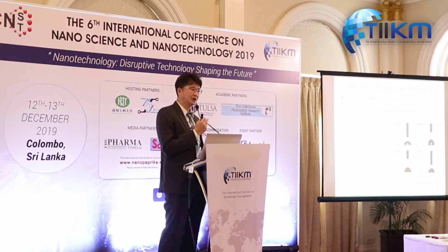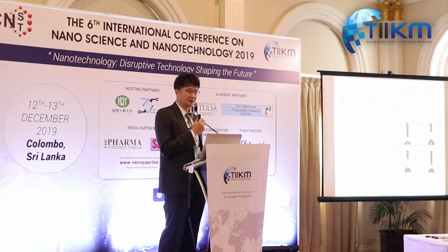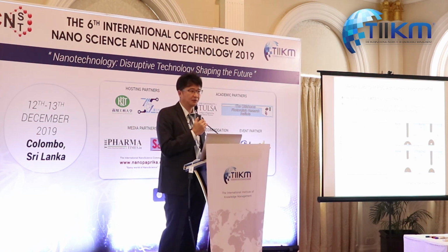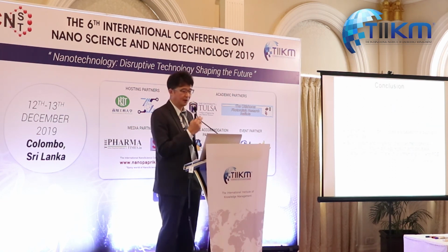So it should be noted that the hydrophobic property for WT3 is large, and this is why the device based on WT3 is more stable than other hole transporting materials, because the hydrophobic property of WT3 can provide better protection of the perovskite layer from the moisture in air, leading to better stability.